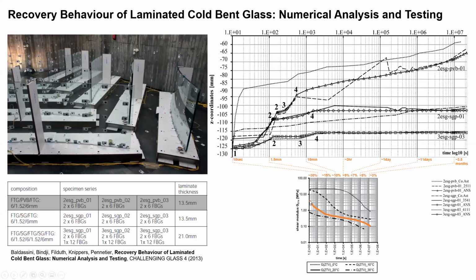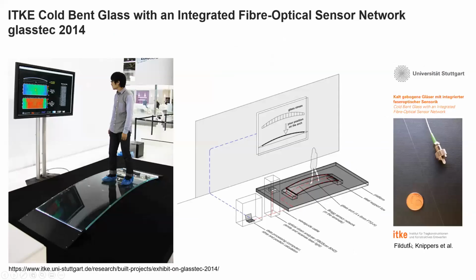And so the interlayer itself lost its capacity, its immediate capacity, if you compare a very short loading of less than a second to a couple of months, you can go from a factor of 1 to 3%. So typically we saw that PVB interlayers became super flat again after basically just a couple of minutes, but that was something that could be leveraged if you had to just place it as an intermediate installation sequence. That could be quite interesting to leverage. But in the long term, the SGP interlayers and SGP laminates behave much better. So I invite you to go and look into more details and ask if you have any questions.